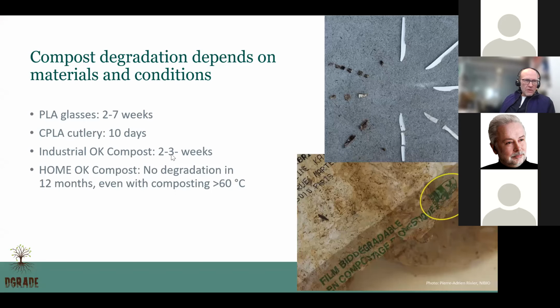So the degradation of the PLA was relatively quick, especially under these industrial conditions when temperatures were reaching between 60 and 70 degrees. We also tested these CPLA cutleries in smaller compost bins, but with the temperature logging and temperatures reaching 70 degrees. And to fragment, we needed some physical breaking of it, but then after about 10 days they were pretty well degraded.